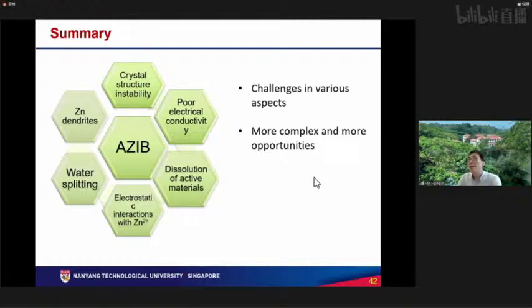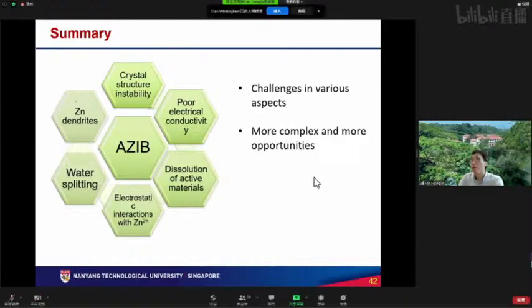So I give a summary: aqueous zinc batteries are very interesting, but you have a lot of challenges. You have structure instability. You have poor electroconductivity compared to most cathodes, especially organic ones. You have dissolution of active materials, manganese, vanadium, all of which are soluble. And we have electrostatic interaction with the zinc ions in the cathode. This electrostatic repulsion is very strong and can cause very sluggish kinetics. That's why people put crystal waters or metal cations into the cathode materials to reduce this strong repulsion. And also water splitting reactions. This is the most serious issue for aqueous batteries, with OER and HER, and we have zinc dendrites.